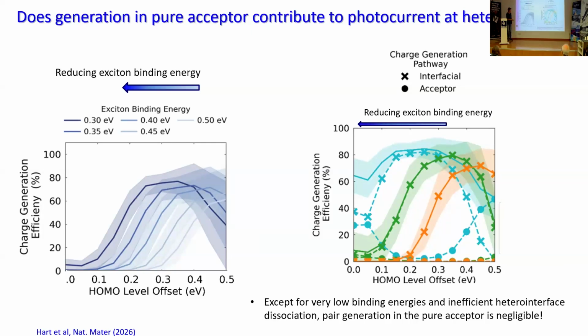So with the model, we see what photocurrent we generate. We can also see where those separated charges were born. Were they born just in the acceptor, or were they born because of exciton dissociation at the interface? And the data on the right are telling us that most of the time, if we ignore the blue curves and just think about the green ones or the orange ones, the crosses are showing us the photocurrent that was born at the interface. And then the dots down here, this is the photocurrent that was born in the acceptor alone. And you can see it's negligible.